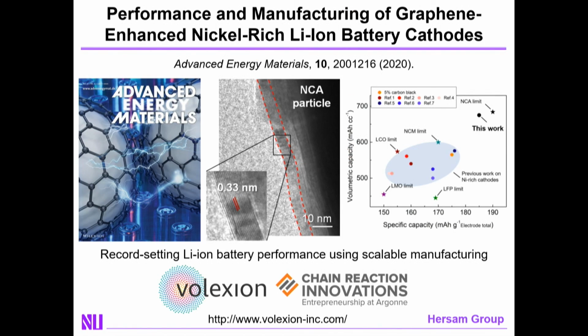Great. Yeah. So am I cherry picking a really nice region? That's a fair question. I would be suspicious too. There's a couple of tricks that give this a very low pinhole density. One is that the size of the graphene sheets is small compared to the surface area of the particle that we're coating. That's actually quite important.